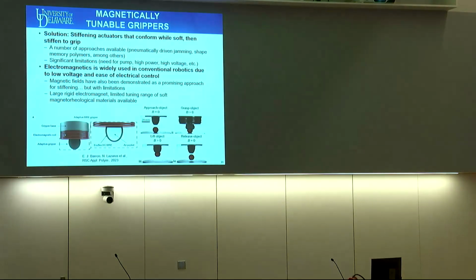Okay. And so using this designed material, we created some magnetically tunable grippers that are able to conform when soft and then stiffen to actually grip the target. What we're seeing here is a gripper base, then a large electromagnetic coil, and then our magnetorheological elastomer around an air pocket that serves as the actual gripper in this particular case. We're then able to use this to successfully grip things like fruit, soft objects, without doing any particular damage. It conforms, grips it, and is able to pick it up, but when you release the magnetic field, the gripper softens and again releases the object.